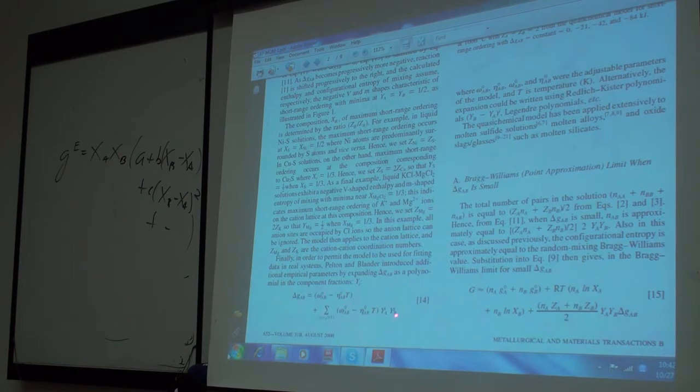What about the next paper? Sorry about that. I forgot, in the next paper we did introduce a slightly better notation, but it's basically the same thing. We just gave different symbols for these. Anyway, this is what we got then. So this is your quasi-chemical term, and this is just a polynomial expansion, so that you can do fine-tuning when you're doing your curve fit. And of course you could add a C log T term too if you wanted, and make a delta Cp not 0. You can do that.